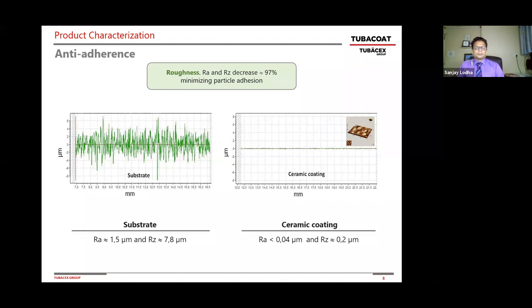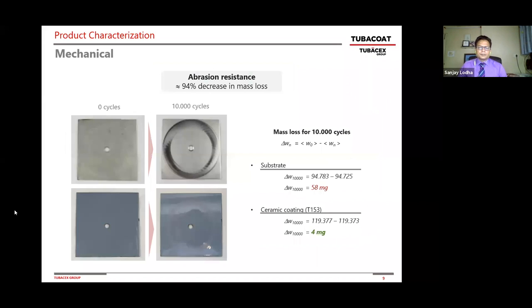Next slide, please. How about the abrasion test? So what we have on the screen on my left is uncoated tube. And at the bottom is the coated tube. And we do an abrasion resistance test, a standard ASTM test with the abrasimeter. And after 10,000 cycles, when I compare the uncoated tube with the coated tube, we see about 94% decrease in the mass loss compared to uncoated tube.